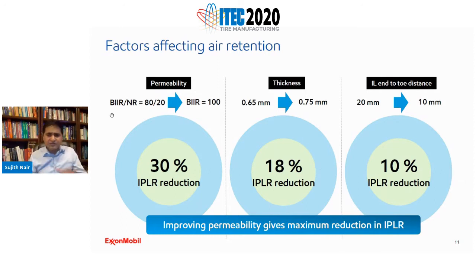So the bottom line is, from all these, you can see that there are multiple ways to improve the air loss performance, but the most impactful way to improve the IPLR is by using a rubber with the lowest permeability. So improving the material composition. That's what's going to give you the best IPLR.